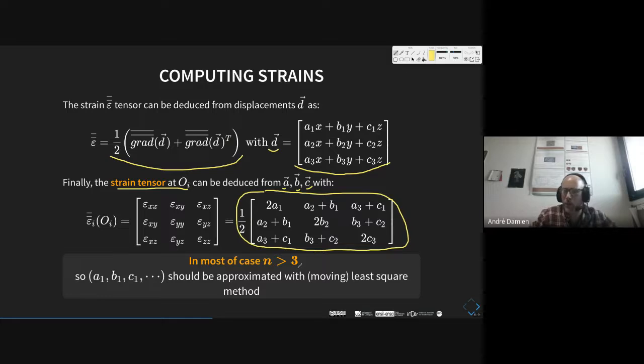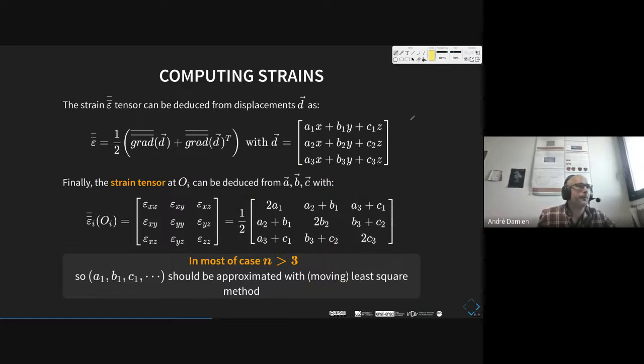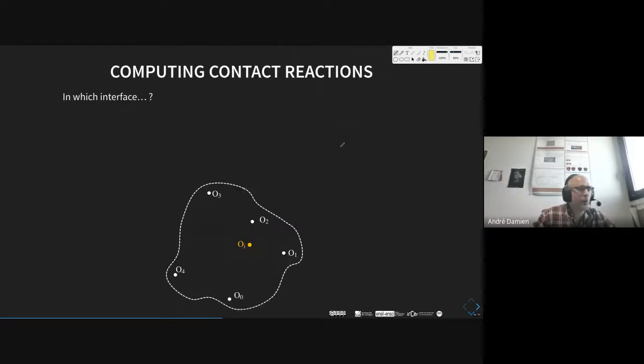In most cases, with a discrete element method in 3D, not in 2D, the number of neighbors that surround a central discrete element is more than 3. So all these unknowns A, B, C are approximated thanks to the moving least square method. Here I insist on this term: it is moving because we apply this method on all the discrete elements. So we have a kind of moving least square method on all the discrete domains. So now we are able to compute the strains of a point cloud.